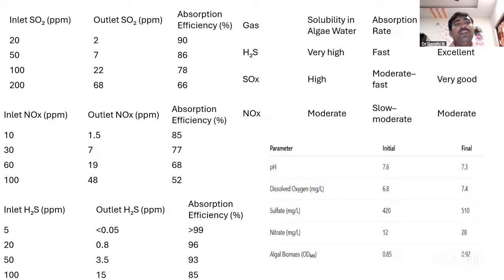So the initial inlet concentration of SO2 we have taken is 20 to 200 ppm, and the outlet concentration is 2 to 68. That means around 66 to 90% of SOx is reduced when we use a volume of 10 liters of gas in a duration of 2 hours. At the same time, we used an inlet of NOx from 10 ppm to 100 ppm because it is a highly concentrated, reddish brown and carcinogenic gas, which creates a good amount of problems for human health.